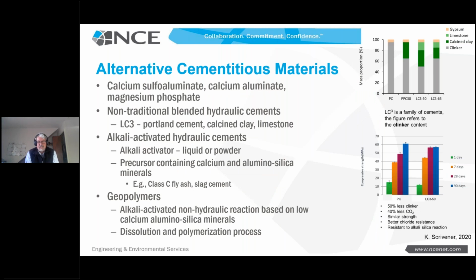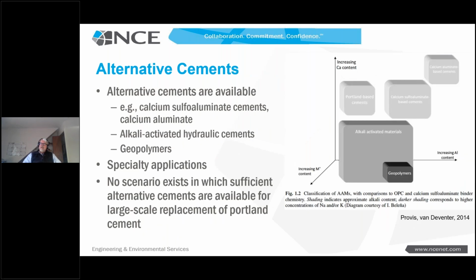A geopolymer is a completely different reaction where, again, we hit it with a highly alkali environment, some kind of an activator to raise the pH of the solution. That will lead to dissociation of the alumina and silica chains that are in some glasses, and these will then start to polymerize. This is, again, not a hydration reaction at all, but a polymerization reaction that creates a very, very durable cement and concrete.